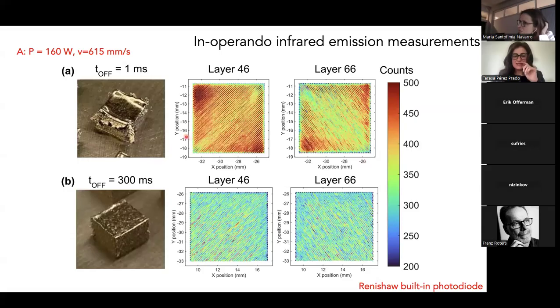First, let's analyze briefly the printability. And I'm showing you here one example. These are some conditions within group A. These were the highest energy conditions. And the first row is without time delays. This 1 millisecond is the default value. So this is without time delays, and here with a time delay of 300 milliseconds. So you already can see that what was before a forbidden region, that wouldn't allow us even to just print the cube itself, now we can process a cube, so this was already good news.